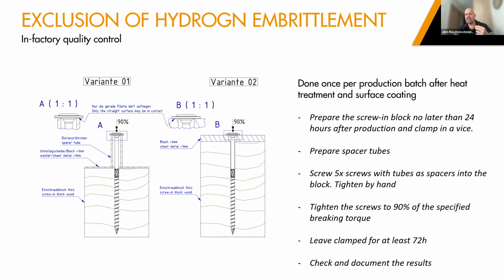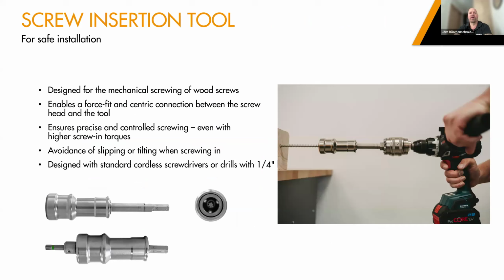Over-torquing is quite a thing. Even a correctly hardened and produced screw free of HE will have a brittle failure when you over-torque it. For this reason, we have 2 little aids. First of all, just a screw insertion tool, which allows you to control the screw more easily. It locks onto the screw and you can handle a longer and higher diameter screw more easily on site, especially on angled installation, working overhead, or without the risk of losing it.